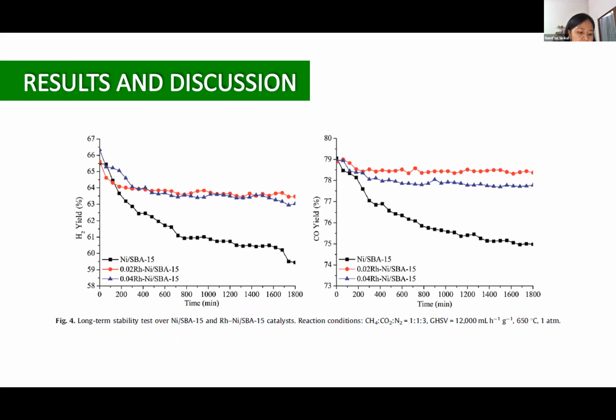Figure 4 shows the apparent deactivation was clearly observed over the monometallic nickel catalyst during the 30-hour time on stream. The yield of hydrogen and carbon monoxide over the nickel on SBA-15 catalyst dropped. It is important to point out that the rhodium-promoted 0.02 rhodium nickel on SBA-15 catalyst is quite stable for the DRM reaction. It can be observed that even when adding a small amount of rhodium, the stability of the bimetallic rhodium nickel catalyst for the DRM is considerably improved with respect to the monometallic nickel catalyst.